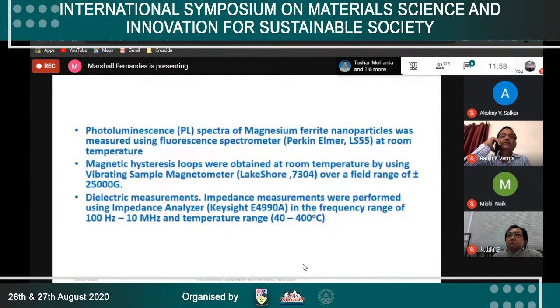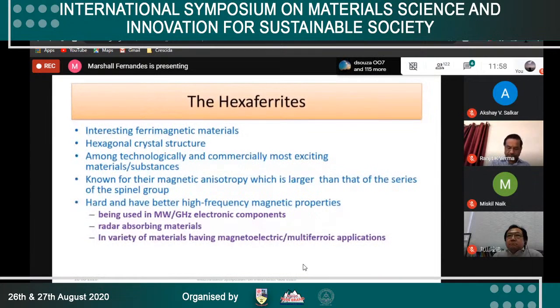The photoluminescence properties are observed with a fluorescence spectrometer, magnetic hysteresis loops, and then the VSM and dielectric measurement. All these things are used for understanding the electrical, magnetic, and optical properties. Hexaferrites, just giving emphasis on barium hexaferrite, I am pointing out how the citrate precursor method is convenient.